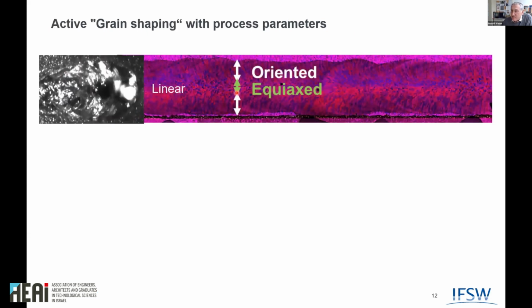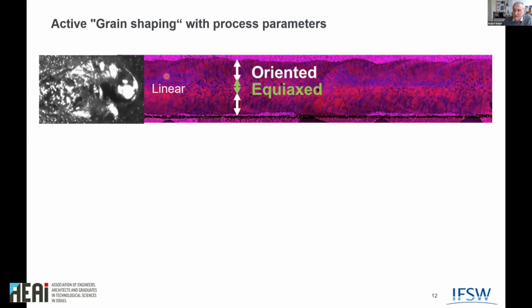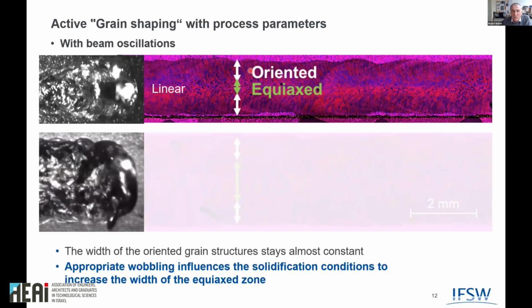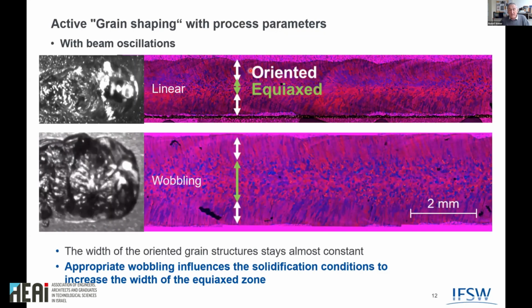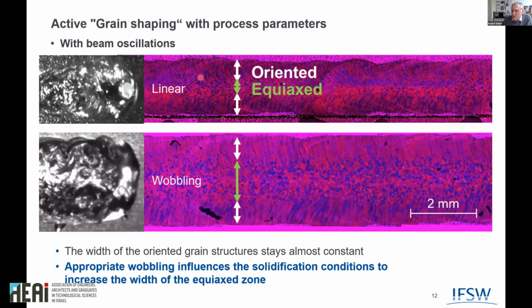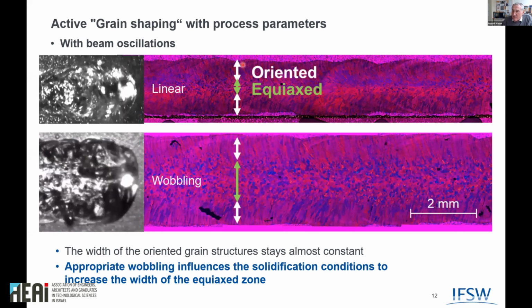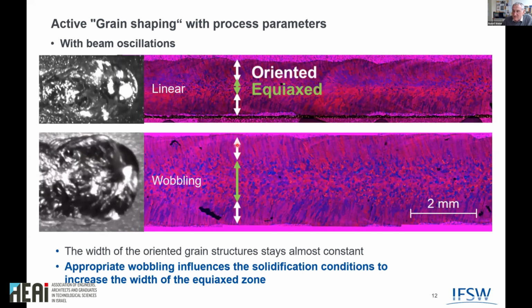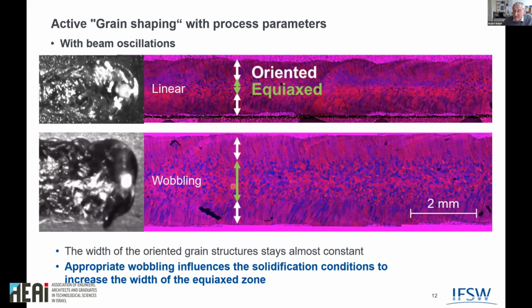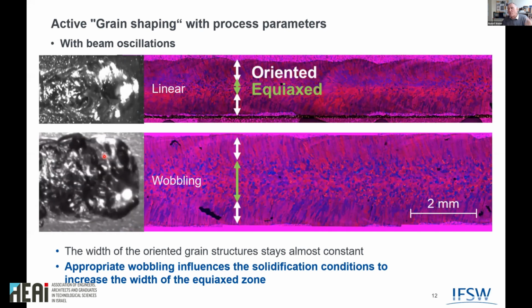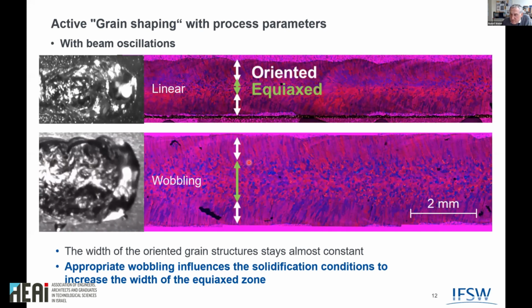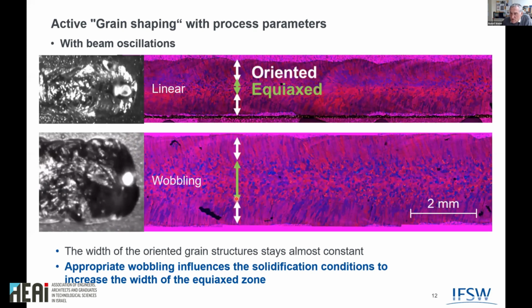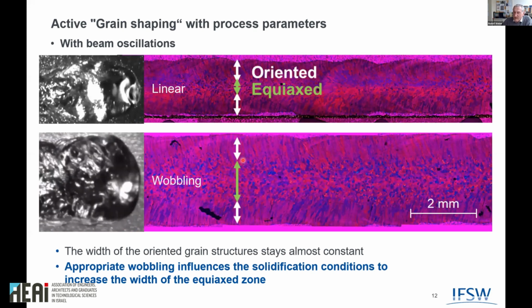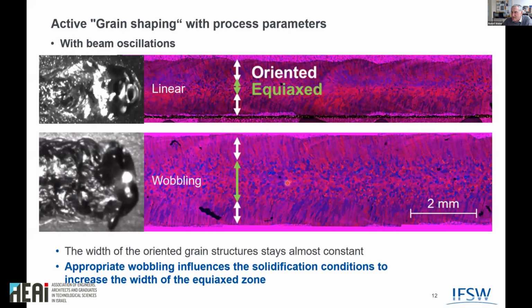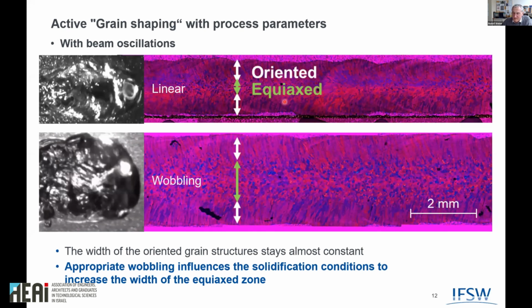This is again the linear weld I have shown already, with a small equiaxed region and a large oriented region. Again, wobbling is one of the first means that you can apply. What you see here is that the oriented part is almost constant. It does not grow or diminish. But by doing the right wobbling, right power, right feed, and so on, you can achieve a much larger area of equiaxed grains, which means this weld is much stronger than this weld.